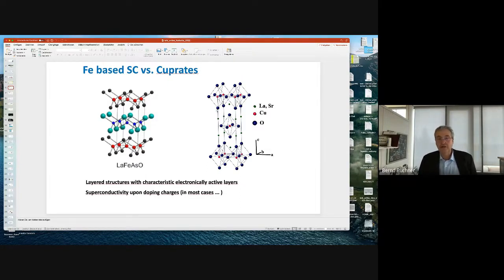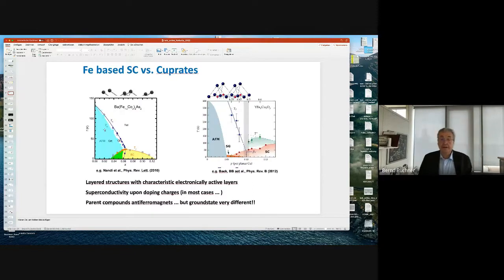Again, we have a layered structure. Superconductivity comes up upon doping, so we have to add in some charges, at least in most cases in these iron-based superconductors as well. But there is a major difference. The parent compounds are antiferromagnets in both cases. So this is an example for this barium 122. You start from an antiferromagnetic state, you dope, and then superconductivity emerges. And that looks very similar to the case of the cuprates. Also, you start from an antiferromagnet, you dope, and then superconductivity comes up, and there's some more complicated stuff which I will not address. So very similar, but the ground state is very different. So the starting points here and there are very different.